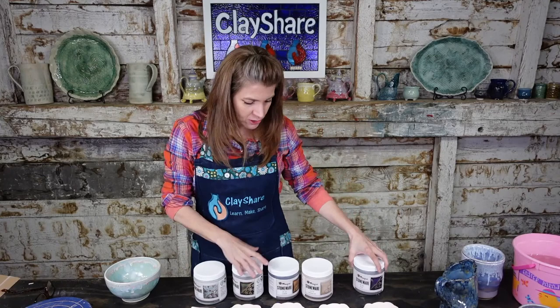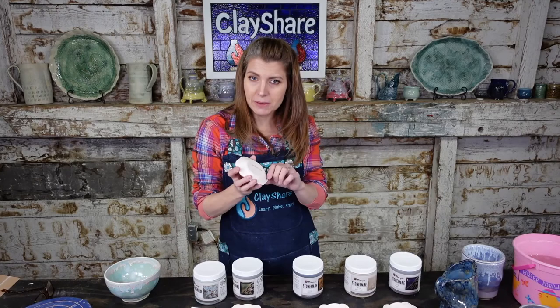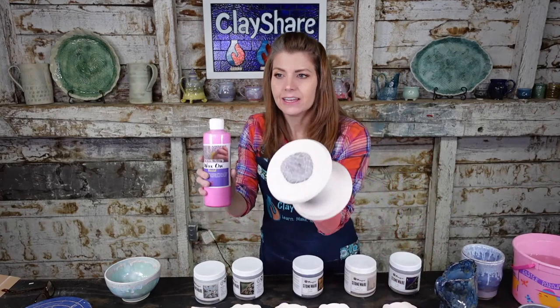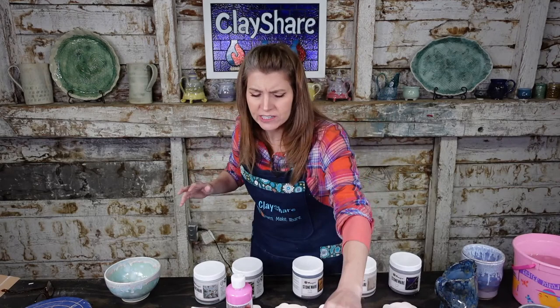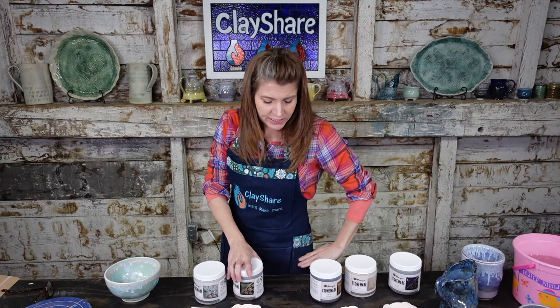It's a very cold, rainy day — that's why I've got hot tea tonight. Now, because these are brush-on glazes, I am not going to wax the bottoms. But if they were a dip glaze, I would wax my bottom so that when I dip it in the bucket, the glaze would be repelled from the base. The wax clouds the clay a little bit, but it burns out at around 400 to 500 degrees — it won't hurt your kiln. It just keeps glaze from sticking to your shelves.